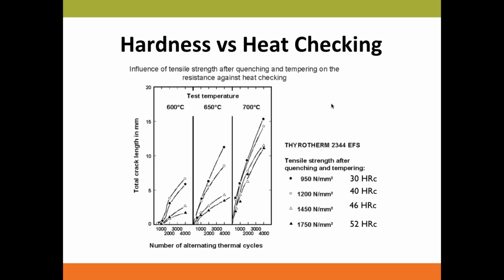And on the left, it shows you the total crack length, meaning if you see little cracks, let's try to add up all the crack lengths together. So that's the total crack length. And I actually converted the tensile into Rockwell, so it's easier for most of us to see. You have 40, 46, 52 Rockwells, and they all have different heat checking responses or resistances.